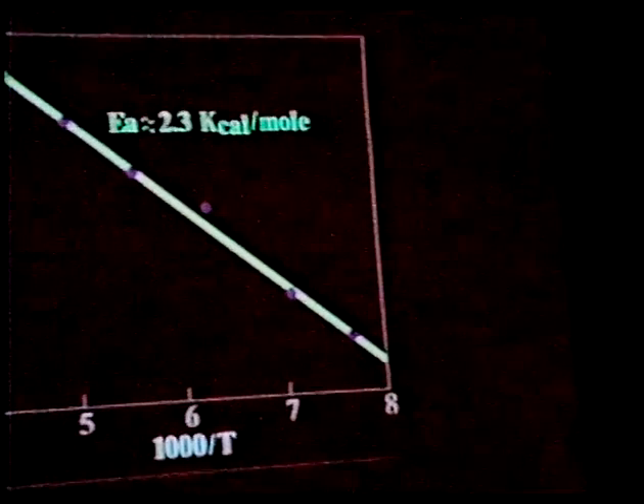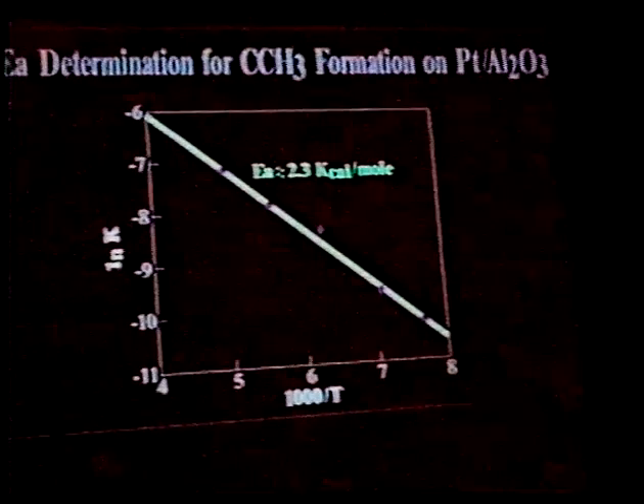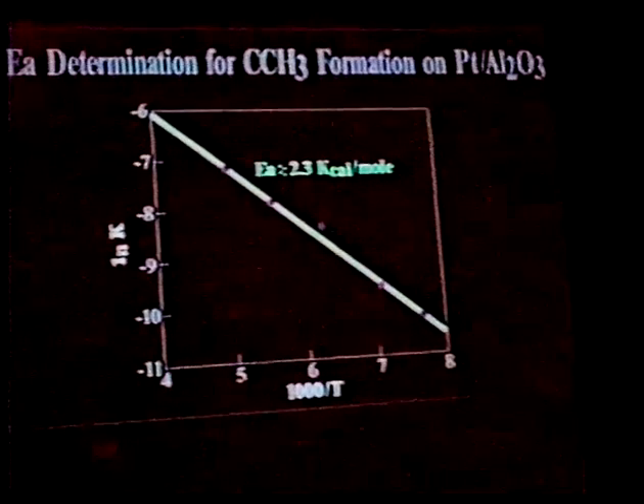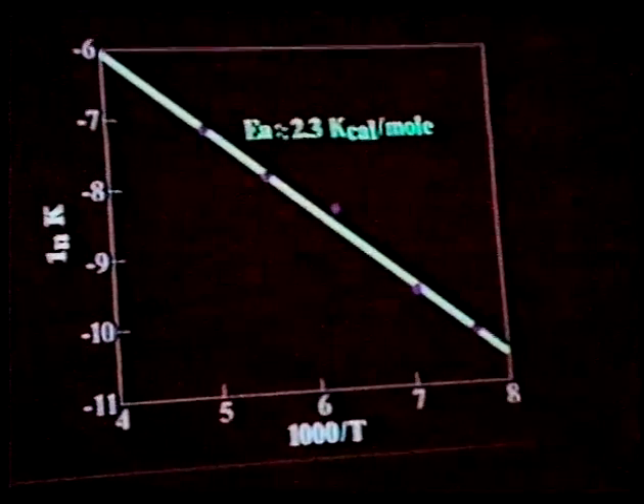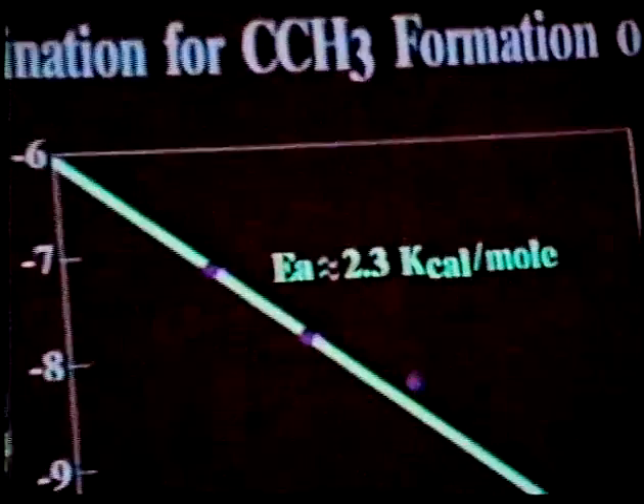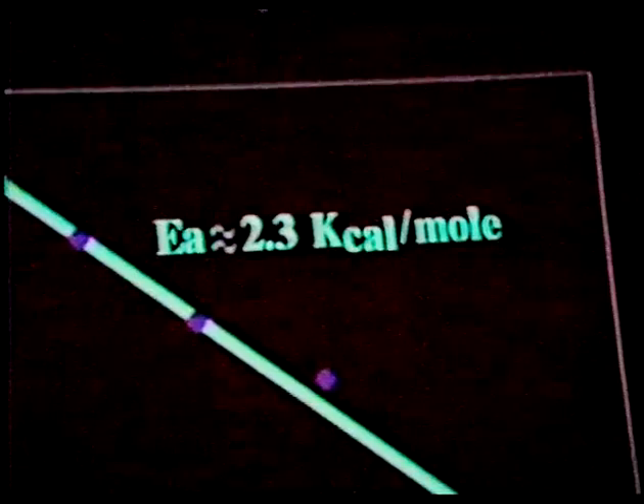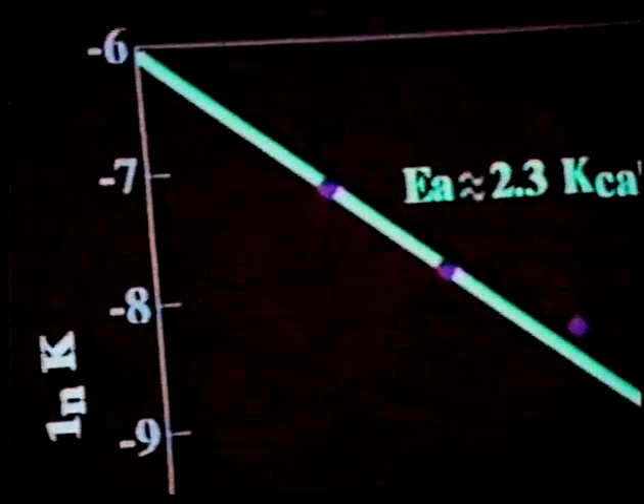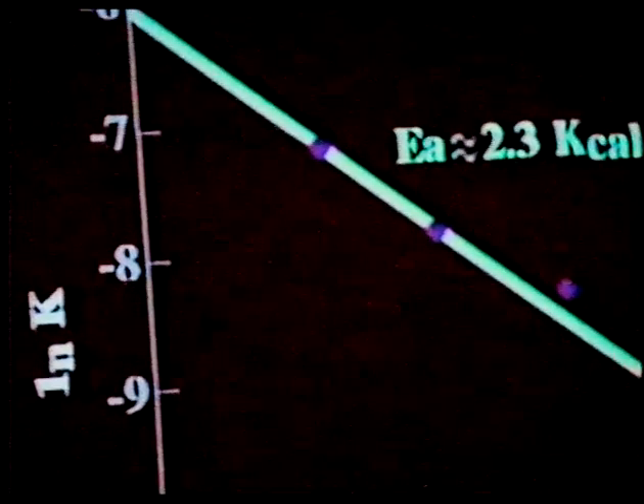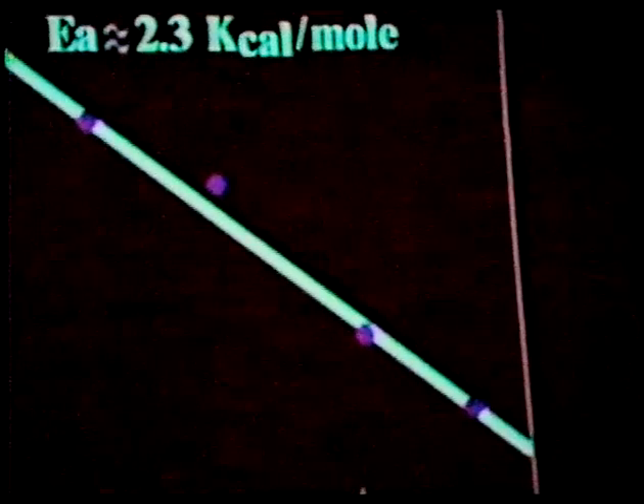And if you do that, it can be done. You can make measurements between about 170 Kelvin and up to about 230 Kelvin, where the process begins to go so fast that you can't really monitor adequately. But what you can see is that you can, in fact, determine an activation energy for this process, and the activation energy is about 2.3 kcals per mole.